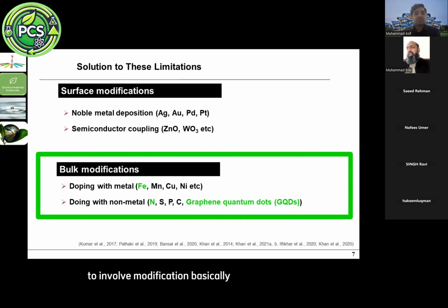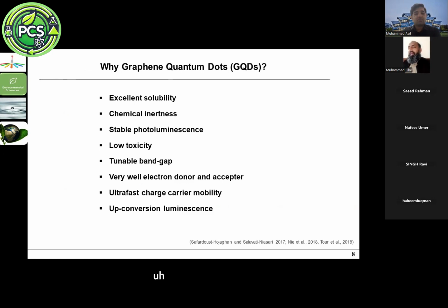In bulk modification, basically, we change the material properties, like we are focusing on titanium. So we change the titanium dioxide properties, both internal as well as on the external surface. In this study, we doped the titanium dioxide with iron from the metals and, from the non-metals, nitrogen and graphene quantum dots as dopant materials. So what is a graphene quantum dot? It possesses some excellent properties like excellent solubility, chemical inertness, stable photoluminescence, and low toxicity. It has tunable band gap properties, very good electron donor-acceptor properties, ultrafast charge carrier mobility, and up-conversion luminescence. These are a few of the characteristics which make this material a good choice as a dopant to materials which are UV active only.